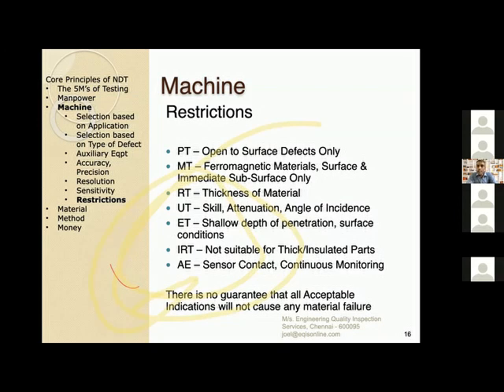And when I say magnetic, obviously magnetic particle testing, it refers only to magnetic materials. And if the material is not magnetic, for example, aluminum or copper, then this testing completely goes to null. It cannot be used at all. And the other restriction is it can go only immediate subsurface. It cannot go deep subsurface.